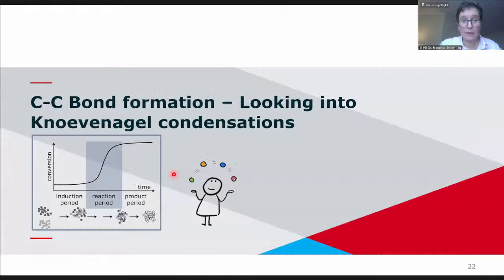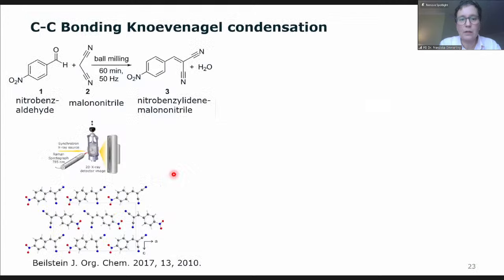Okay, so we switch gears a bit and look at the CC bond formation. We spent quite some time looking into the so-called Knövenagel condensation. And here you see the reaction we were looking at. That's nitrobenzaldehyde and malononitrile. You have to mill it for around 60 minutes at 50 hertz, and then you end up with this compound.